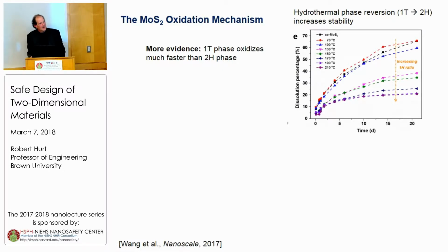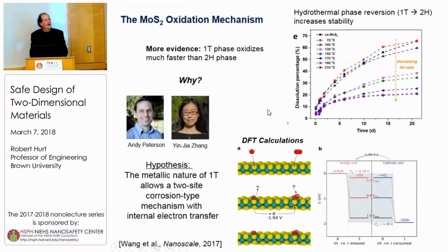You can actually see that directly by taking the metallic phase, hydrothermally converting it to the semiconducting phase, and then looking at the rate of oxidation and dissolution. As you make that phase reversion, as they call it, you can reduce the rate at which these things oxidize. So why in the world is the oxidation rate for molybdenum disulfide dependent on this phase? Maybe in biology we wouldn't care, but it's an interesting question for the field.